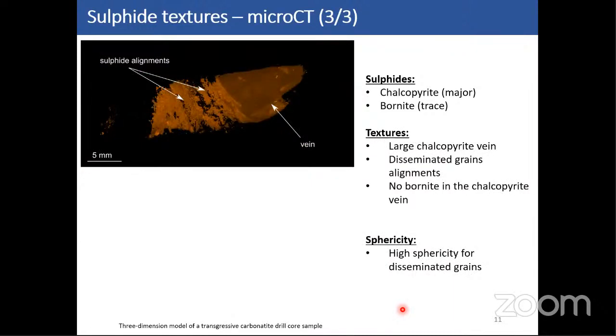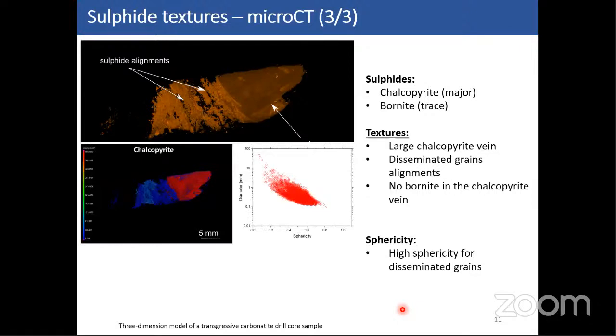Something interesting with a transgressive carbonatite sample, as you can see here on the right: there's a presence of a chalcopyrite vein. And something also interesting is the presence of disseminated sulfide alignments here, parallel to the vein. It reminds me a little bit of the transgressive carbonatite block for mineral liberation analysis with mineral mapping. However, the main difference is that the sulfides in proximity to the vein are classified as disseminated grains, which means that, according to this classification, they have nothing to do with the vein itself. Otherwise, it would have been assimilated to the volume in red.